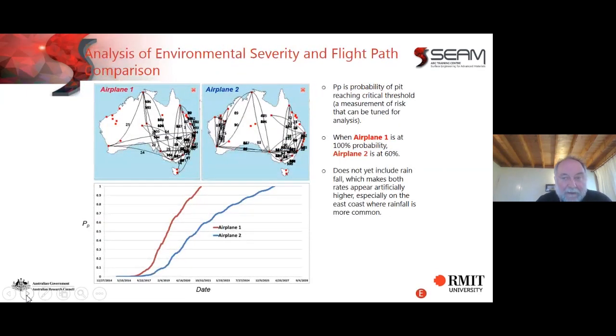Having combined all that, we can then look at the life of the inhibited paint film, and we can look at it as a function of the flight pattern of the aircraft. Now, this was a particular, not so much test, but a problem. They had the same aircraft flying on two different aircraft routes, but they found that one of the aircraft was corroding at a faster rate than the other, and they couldn't understand why. So they came to us and said, the airplane number 2 flying on these routes is not corroding, whereas aircraft 1 flying on these routes is.